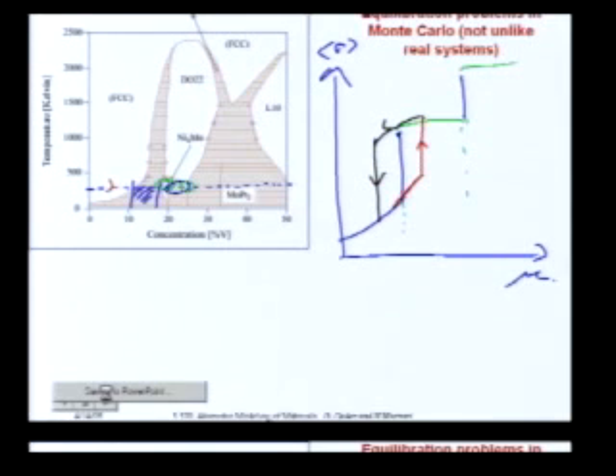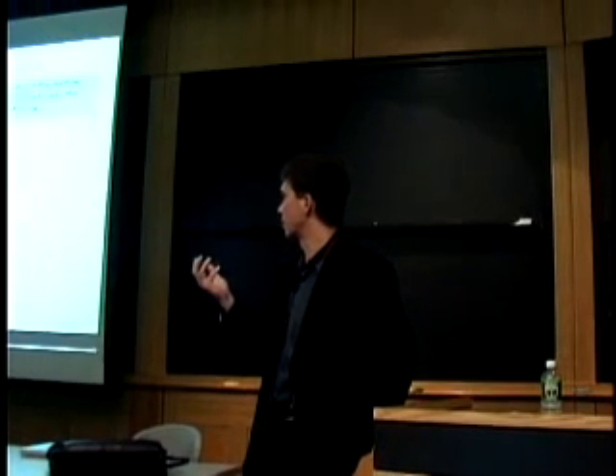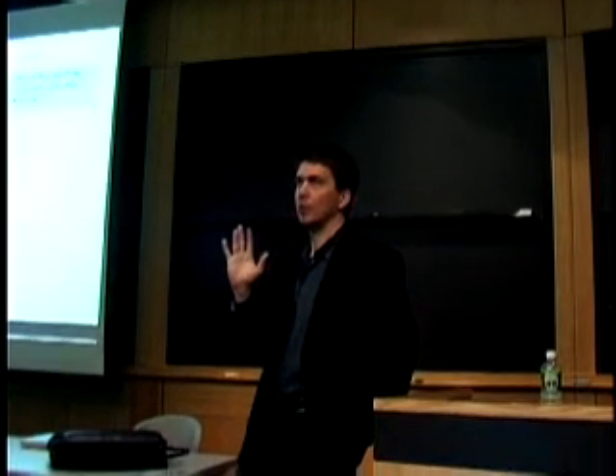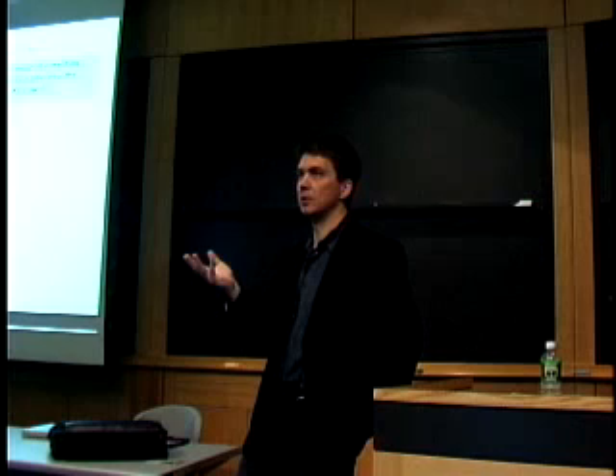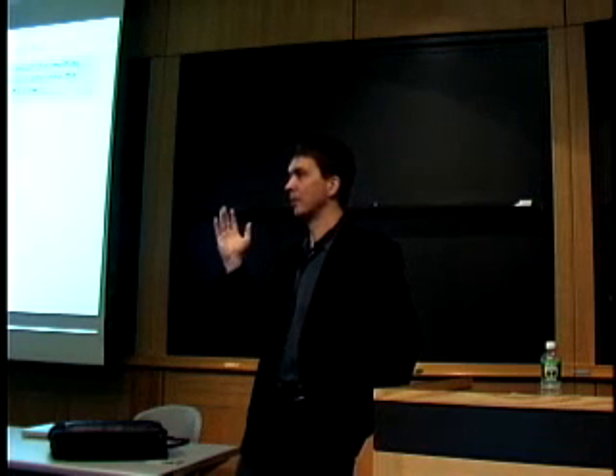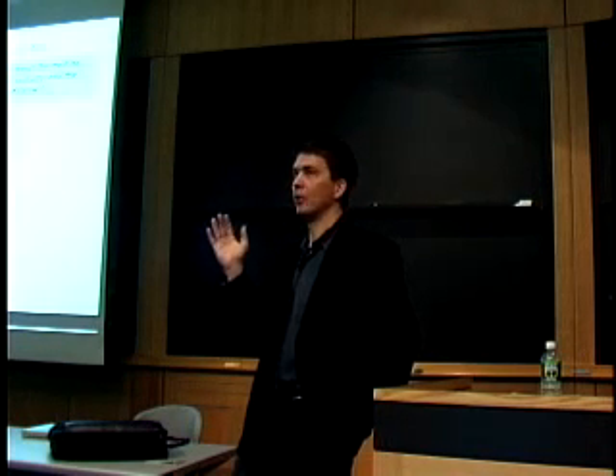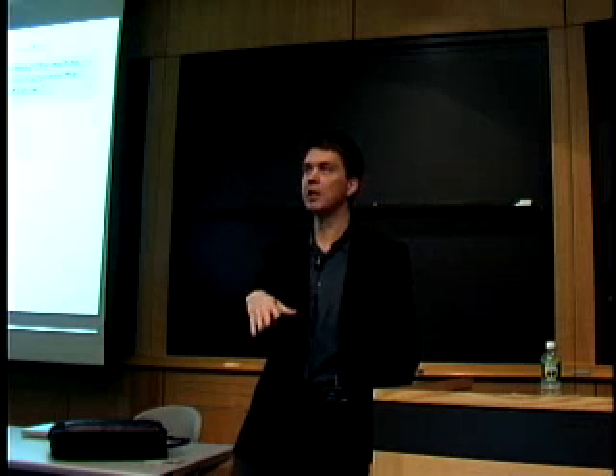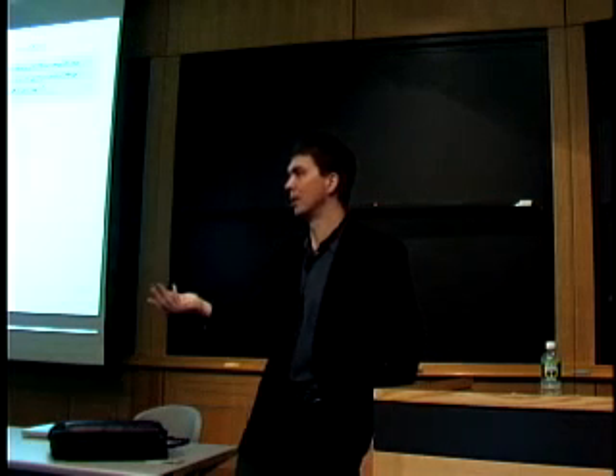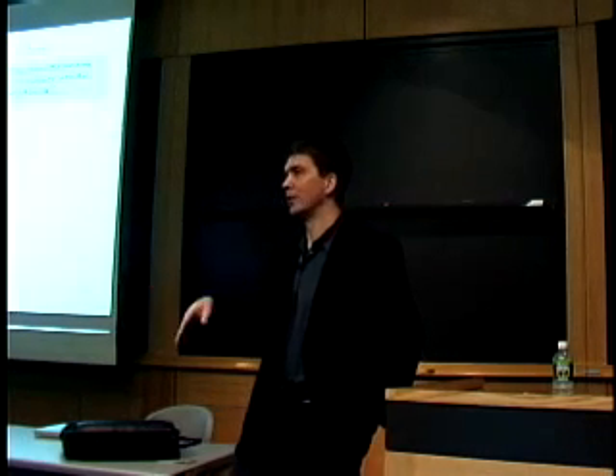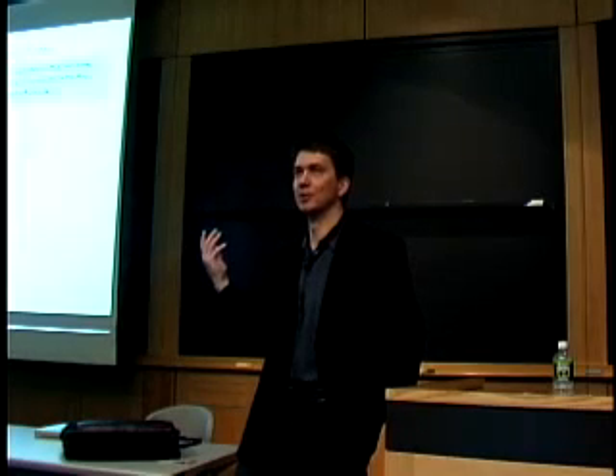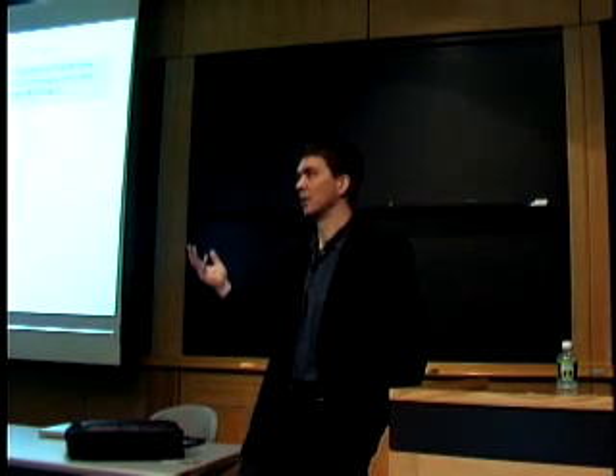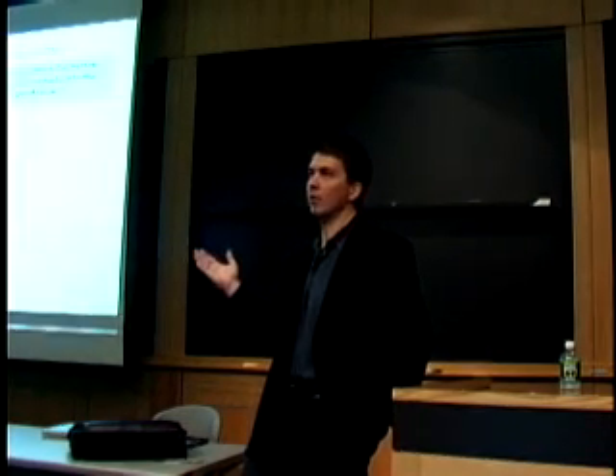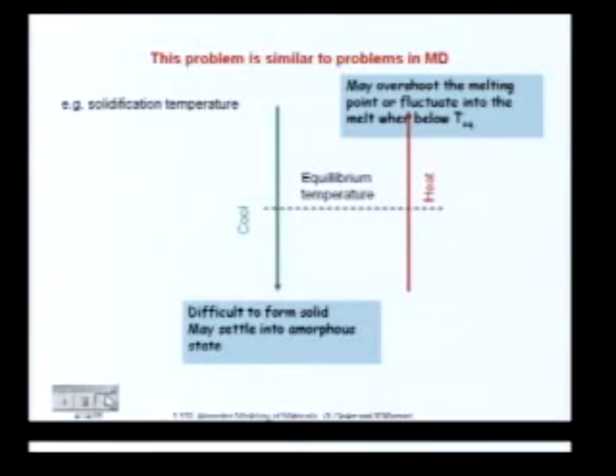I think some of you may have noticed that if you did the molecular dynamics lab. Seeing first-order transitions in a molecular dynamics lab, you also are often plagued with hysteresis. I mean, if you study melting, for example, it's very asymmetrical hysteresis. If you heat up a solid, it's pretty easy to melt it. If you cool down the liquid, it's about impossible to nucleate the solid, unless you force it. So there you have enormous amounts of hysteresis.